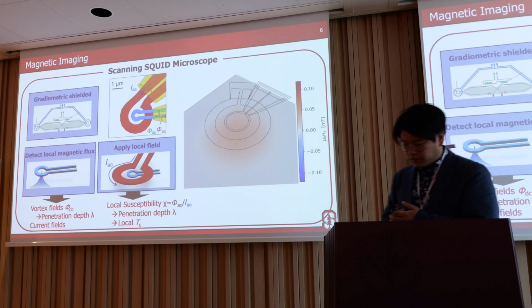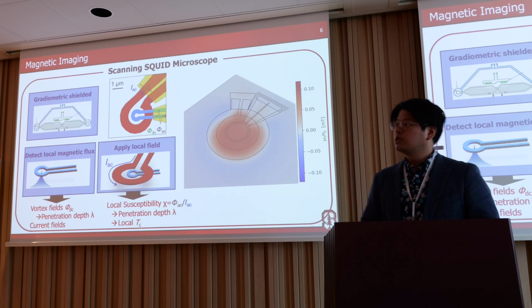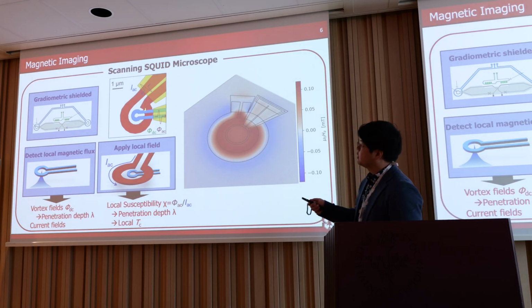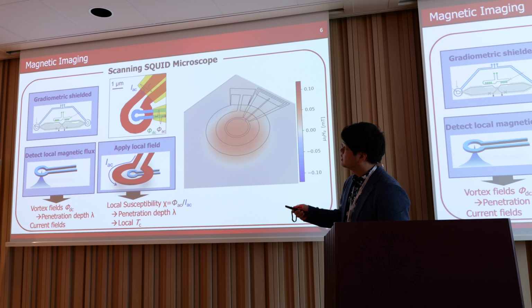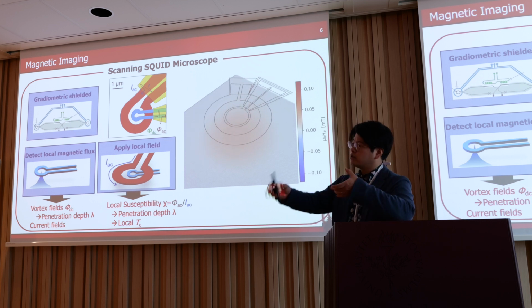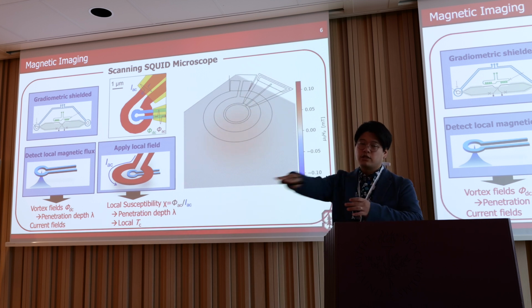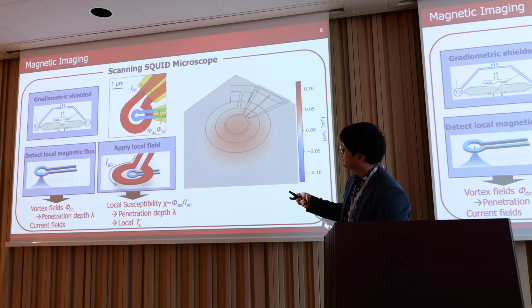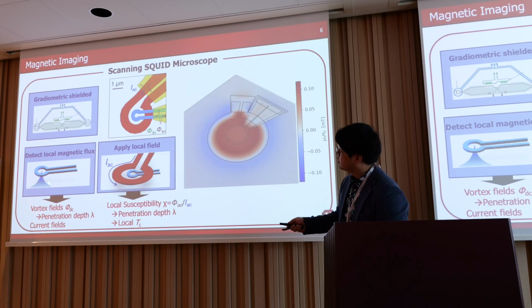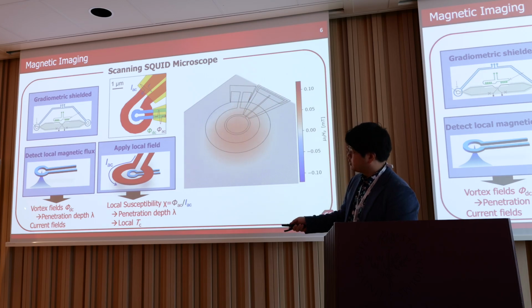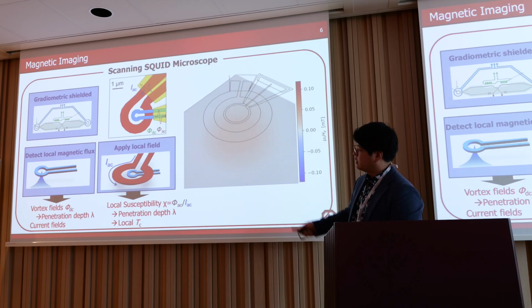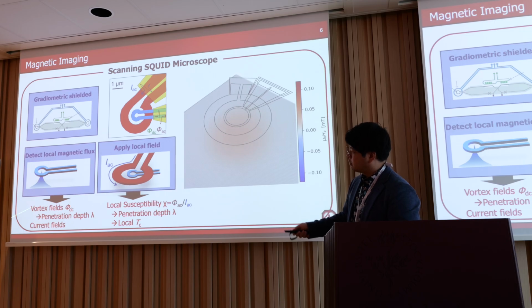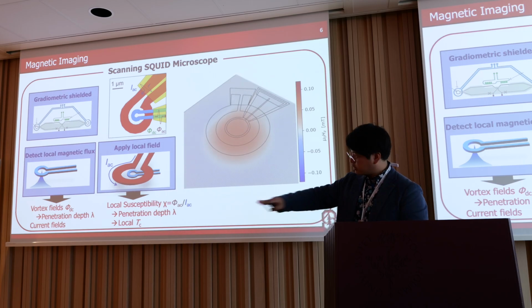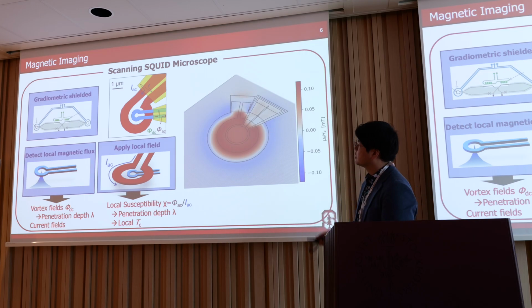Okay, so here we use a scanning SQUID microscope. Our SQUID is a small pickup loop in a SQUID circuit, and it has a gradiometric structure, so it cancels uniform field. And also there's superconducting shielding, so only the magnetic field goes through this pickup loop. And then we locally visualize the vortex field and detect the penetration depths, or measure the magnetic field from the current.